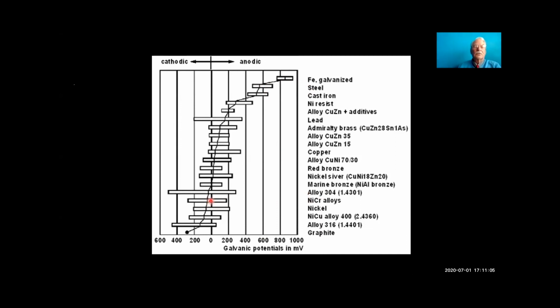So that you can see that between stainless steel here and the ferrous materials up here, there is 500-600 millivolts. That's half a volt. That is a very significant potential. And so the corrosion between the ferrous material and stainless steel bolts or any other parts, any other sections of stainless steel can be very high.